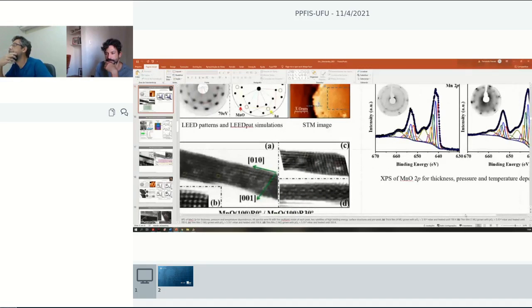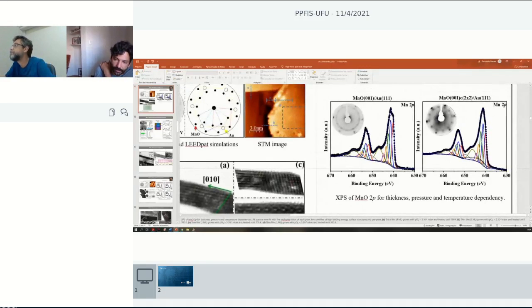So, can you see here? Yeah. More details, right? So what you have to do here is you need some guesses. So this is one type of peak deconvolution. We do not use that very often, but it is an empirical model based on the multiplet splitting. So it depends on how the electrons are created, extracted, and how many holes you have in the 2p level. So you have 6, let's say, boxes, right? 4 for the 2p 3/2, 2 for the 2p 1/2. So to get the 2p orbitals, you know how many electrons should be there. But then you have an oxide, so it's not a metal. So you have a spin-orbit splitting, because you have the interaction with the crystal field of the oxide. So now you have the levels, and then you have to occupy them. That's why you have boxes where you can put 2 electrons in each one.